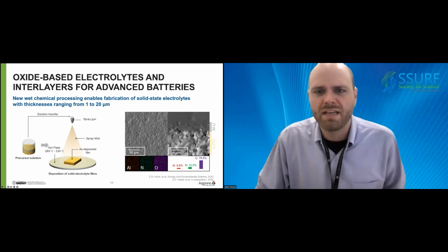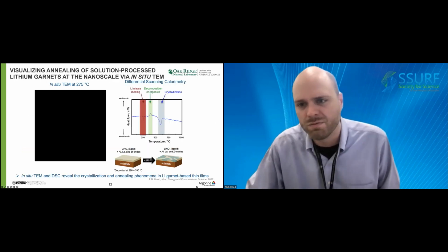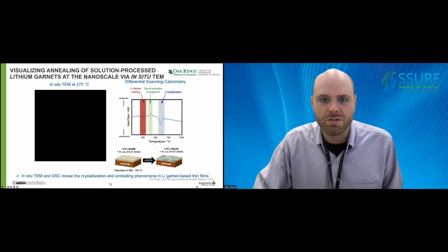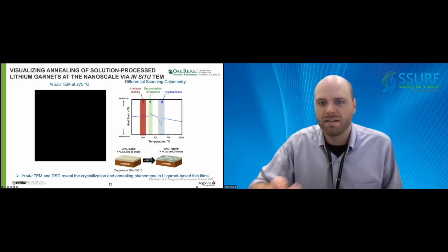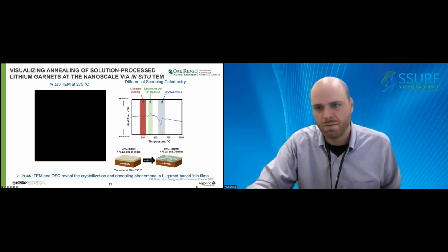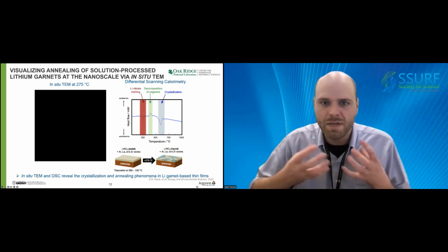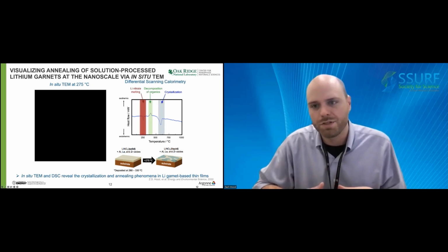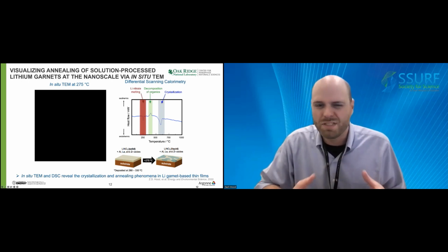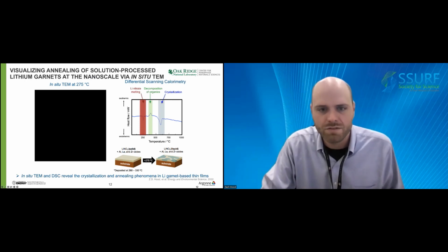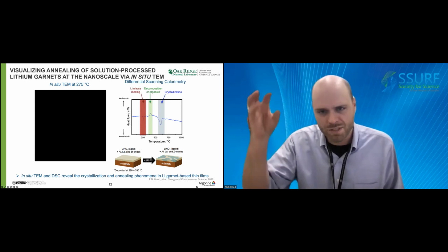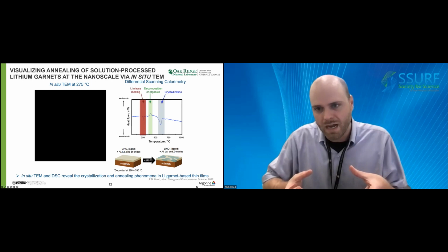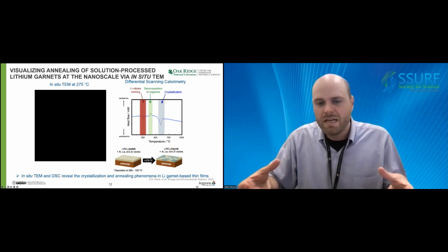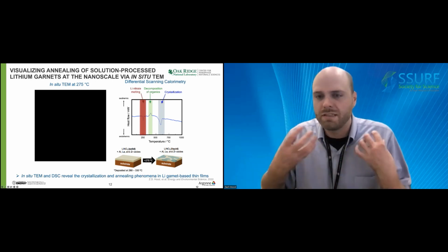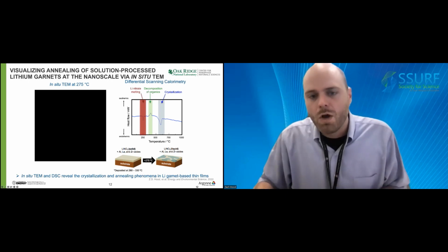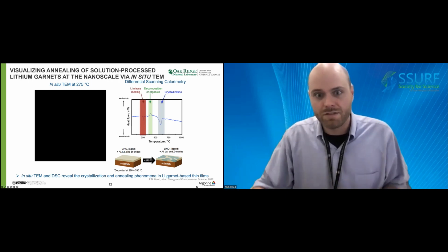So we further investigated the dynamic processes during the film formation using differential scanning calorimetry. Here I want to highlight a few of the main processes. With differential scanning calorimetry, we can measure the heat flow as a function of temperature. Here we can see a few specific endothermic and exothermic events. Remember, we can first deposit our film onto a heated substrate, and then depending on what type of crystallinity we desire in these films, we can then heat it and crystallize our films.